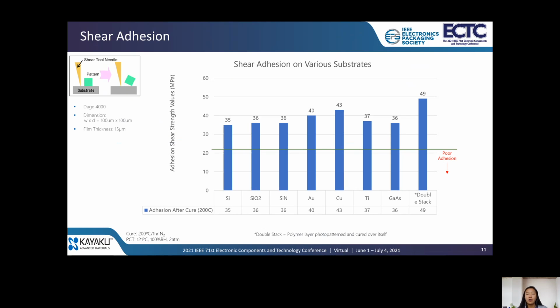So another important part for dielectric materials is adhesion, and it's an important parameter really to understand the behavior of the material to metals or other inorganic substrates it may interact with in a device. PRL 29 was coated on various metal, inorganic and organic substrates, processed through soft bake, exposure, PEB, development, and cure. So the material, as you can see on the left schematic, was patterned to achieve 100 micron by 100 micron post structures at around a 15 micron film thickness.